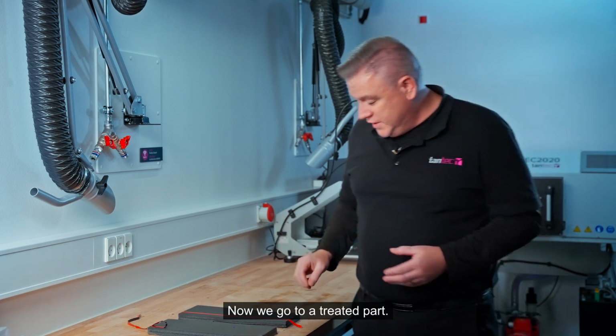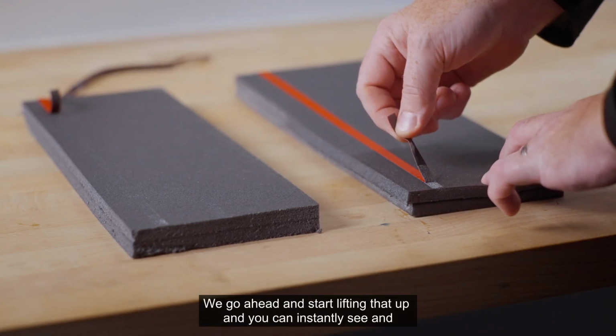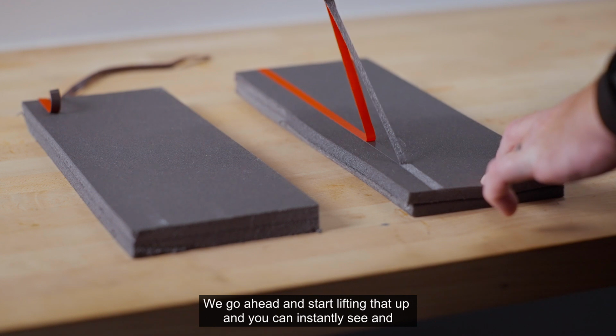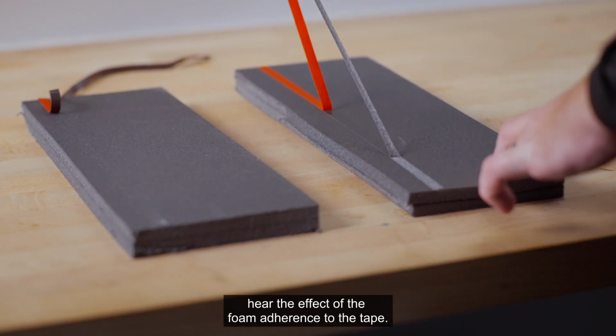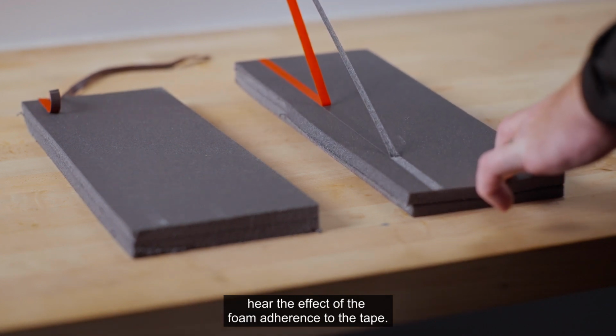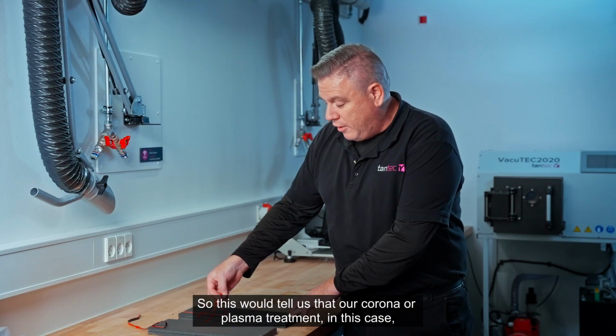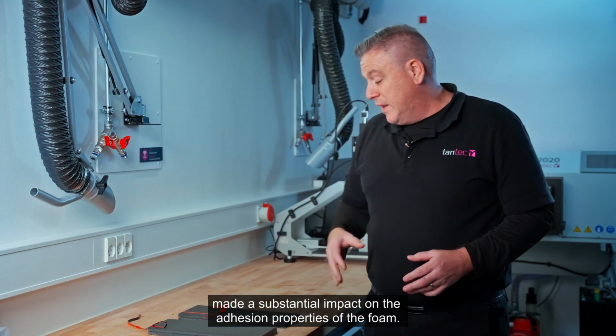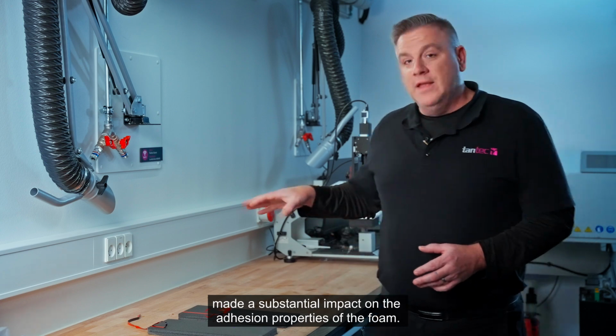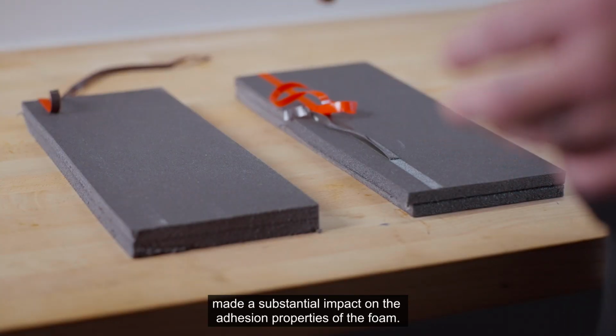Now we go to a treated part. We go ahead and start lifting that up and you can instantly see and hear the effect of the foam adherence to the tape. So this would tell us that our corona or plasma treatment in this case made a substantial impact on the adhesion properties of the foam.